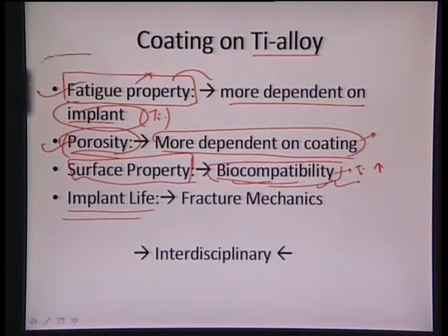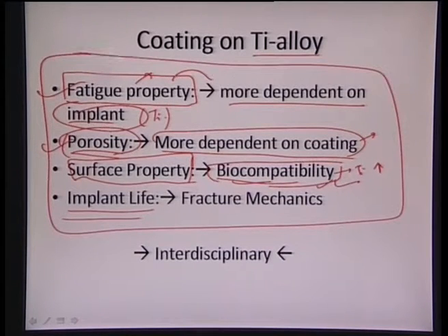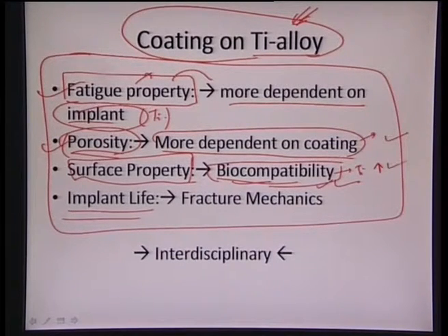So there are certain aspects to the titanium alloy which make it a complete implant which can be inserted into the body. These coatings on the titanium alloy are one of the very essential components, because they take care of porosity, they decide the surface property, and they also decide whether cells will be more compatible or not. They can also induce some sort of porosity in the material, and they can enhance the wear resistance of the material. They have to be the ones which see the direct environment. So the coatings are one of the very essential components of the implant as such.